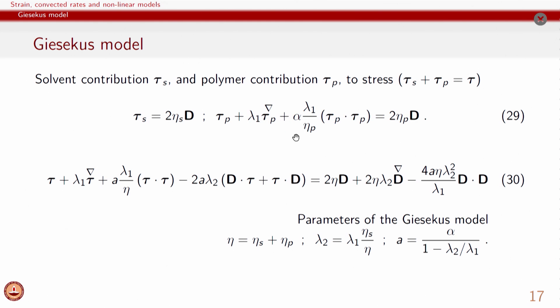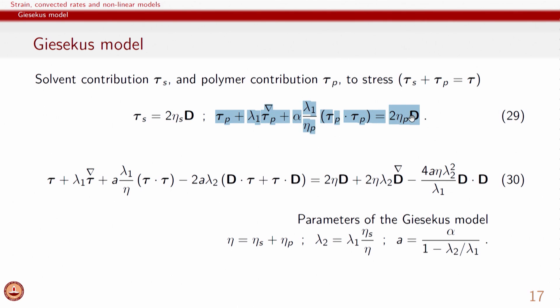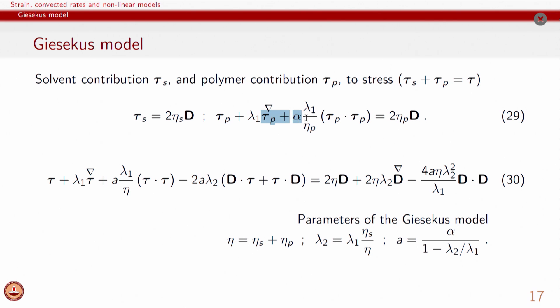The model incorporates the mechanisms of stretching and orientation of macromolecules. Whenever a polymer solution is being deformed, the macromolecules can stretch and orient, giving rise to the upper convected Maxwell model of polymer contribution stress. Additionally, there is a nonlinear term where alpha is the most important nonlinear parameter. If alpha is zero, the overall governing equation reduces to the Oldroyd-B model — combining the solvent Newtonian contribution and the polymer upper convected Maxwell contribution. Oldroyd-B model is only a very qualitative descriptor of overall rheological response, with many of the same limitations as the upper convected Maxwell model.